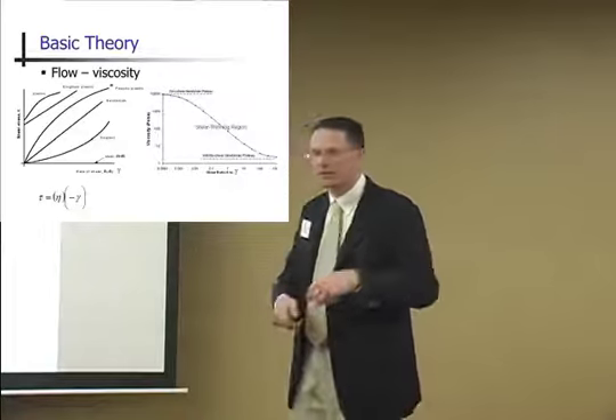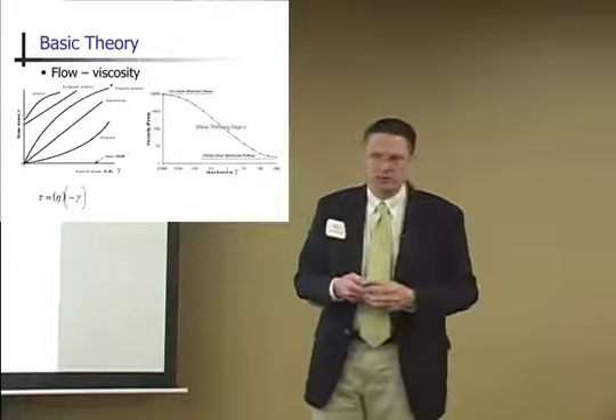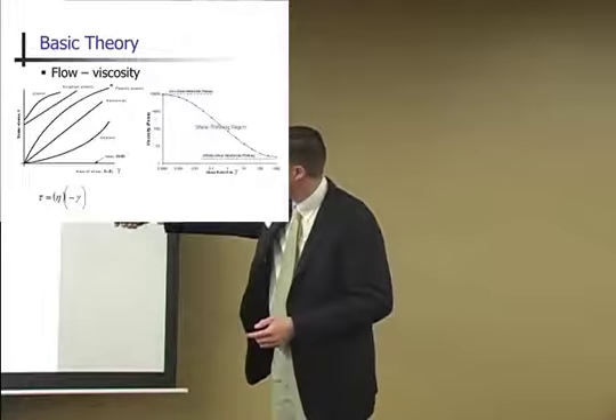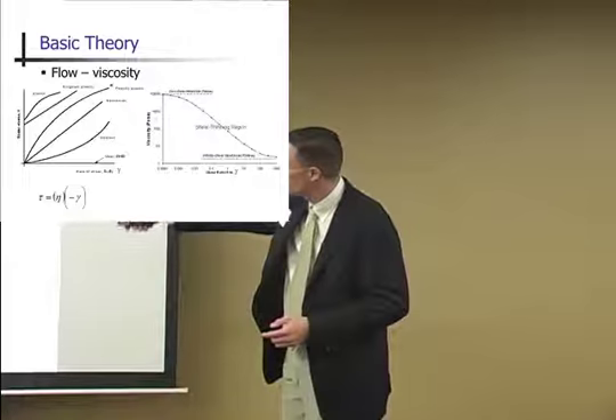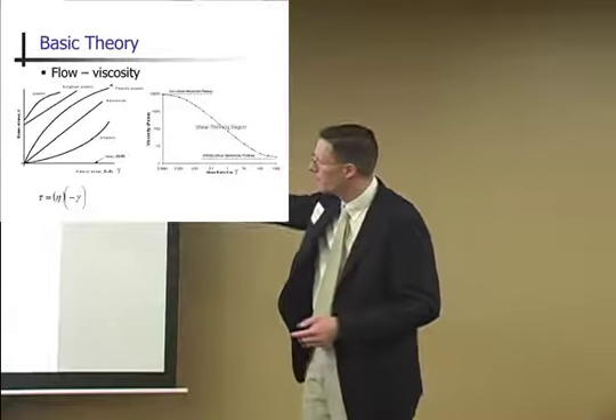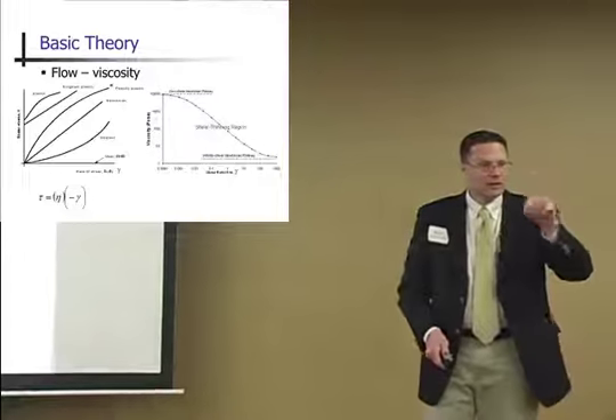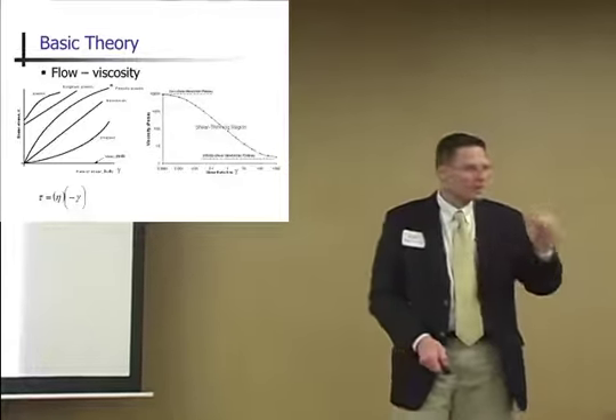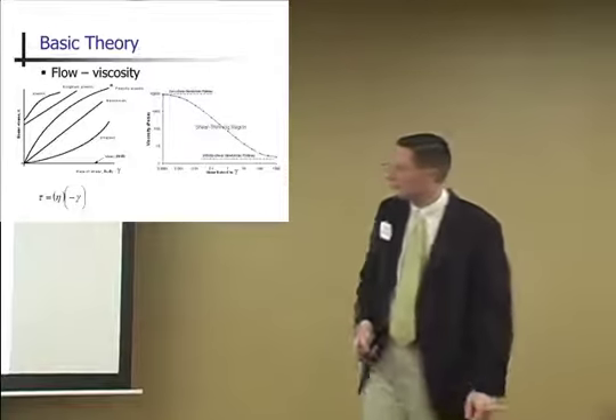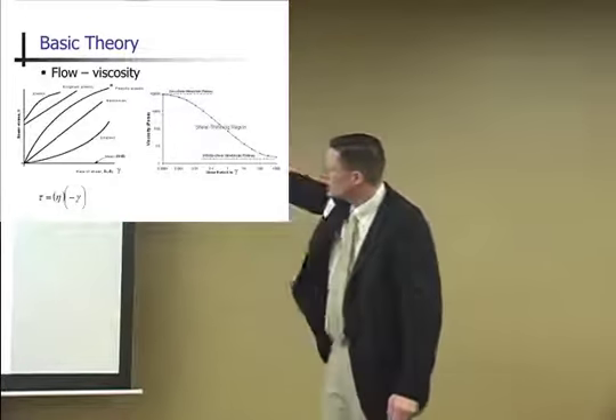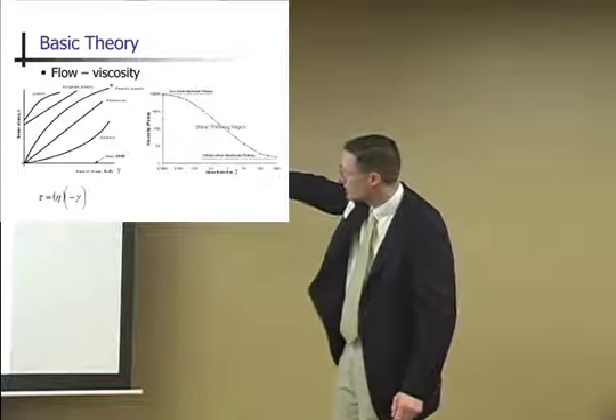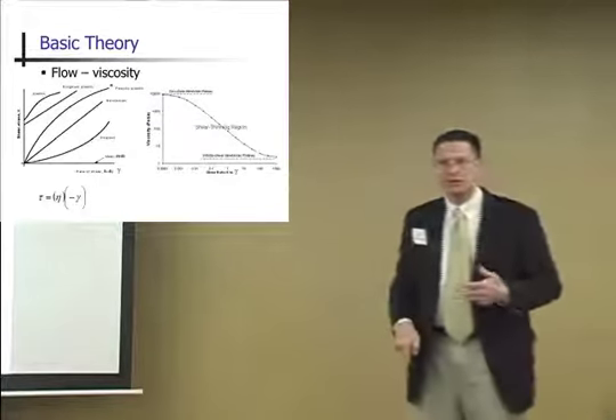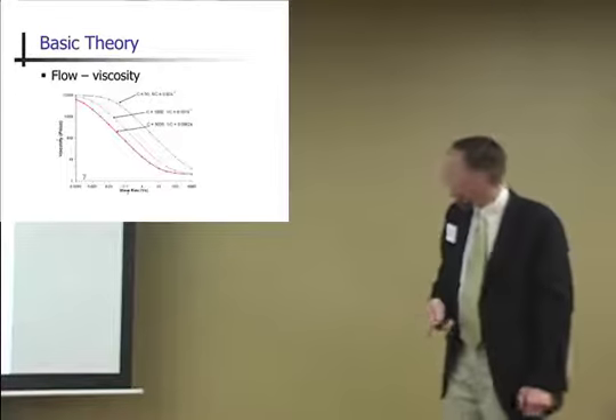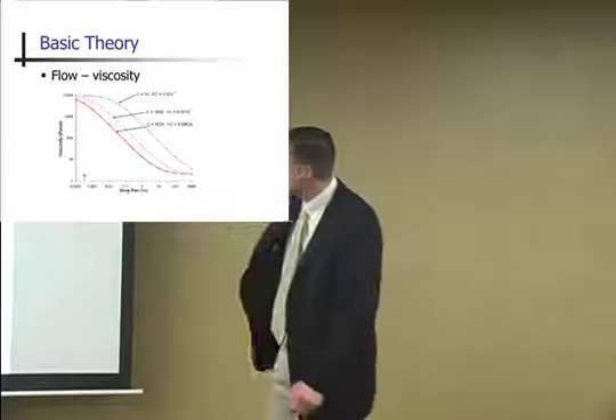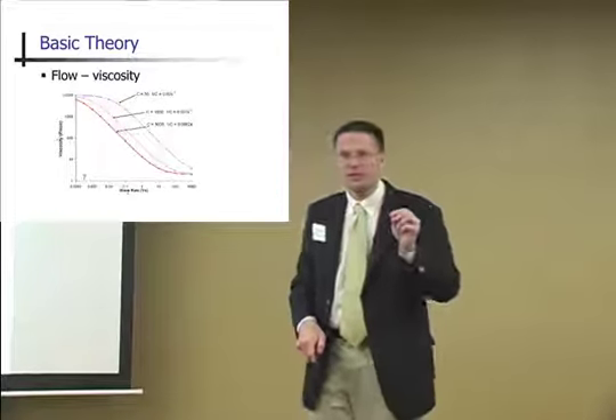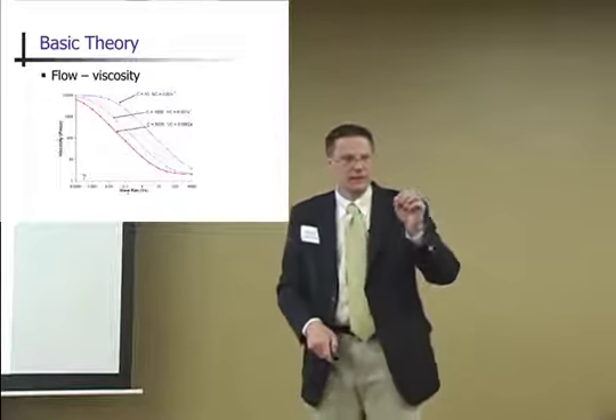Now, there are all sorts of fluids in this world, and most feed ingredients are what we call pseudoplastic. The faster you go, you're going to get an increase, and then it's going to level out. So the faster you go, the easier it is to push that fluid. The slower the flow, the more resistant, the more energy it takes to move that fluid. So basically, if you take a look at viscosity, this is speed, viscosity decreases non-linearly the faster you move that extruder screw. So viscosity changes not just with speed but with temperature. The higher the temperature, the lower that viscosity.